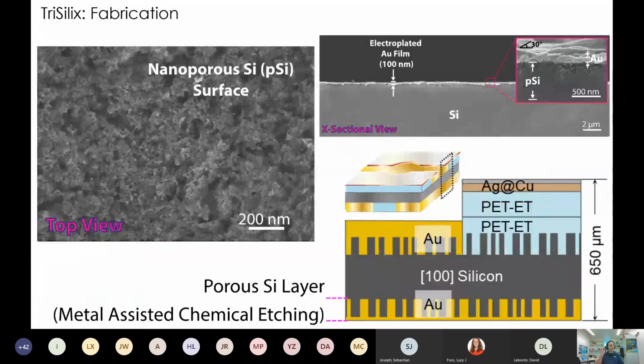And one of the enabling things about fabricating these chips was to create a nanoporous silicon surface, which allowed us to electroplate materials on silicon very easily in the lab. Because if you have a silicon wafer that has a very flat surface, it's really hard to electroplate metals on a flat silicon surface, because they just peel off. So we have come up with a strategy to overcome this by creating a nanoporous surface so that when the metal is electroplated, it creates interlocking structures.